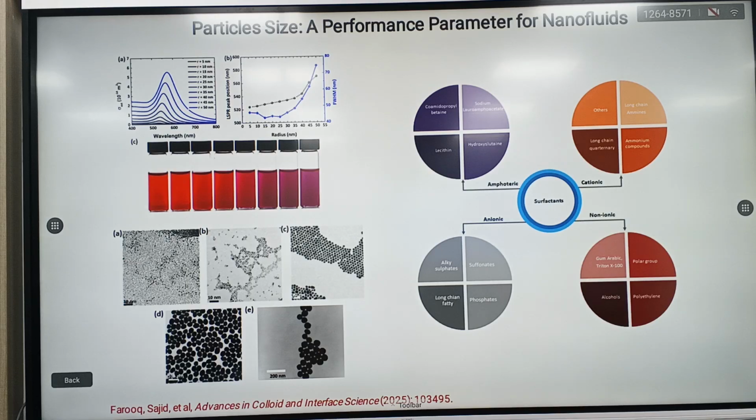If we are working with gold nanoparticles, we know that the wavelength spectrum shift is between 510 and 576, maximum. But the solar spectrum starts from 350 and goes to the infrared, right? 85% of the solar spectrum energy is around 350 to 1200 nanometers.